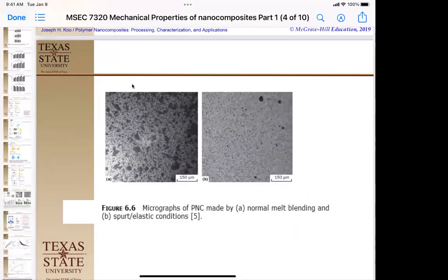Okay. In this one right here, they were doing a polymer nanocomposite. I want to say it's nylon 6, and they have nanodiamonds. Okay, nanodiamonds are nice spherical hard particles, very good density, very good heat transfer. And they were doing it by extrusion systems where they do the normal melt blending here. And then they were going, yeah, this dispersion's okay. We see some of the larger particles, some of the smaller particles. It's okay distributed. But then they had a problem in the machine.